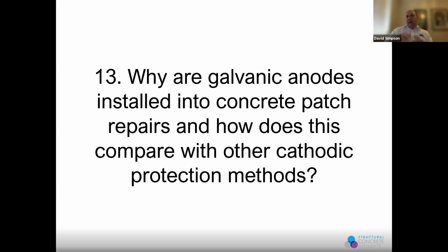So in this position, it's not cathodic protection in terms of corrosion occurring. It's in the cathodic prevention realm again. We're trying to prevent the steel from corroding on the outside of the patch. And galvanics, because of their limited voltage and their simplicity... you could do this with impressed current cathodic protection. You could protect patches with impressed current cathodic protection. It's probably not the most cost-effective way of doing it, hence why galvanics were really used in that sense. They were installed, you covered them over, they provide protection to the steel, prevent it from corroding, and extend the life of the repair. And typically, probably globally, the biggest market for galvanic systems remains in this